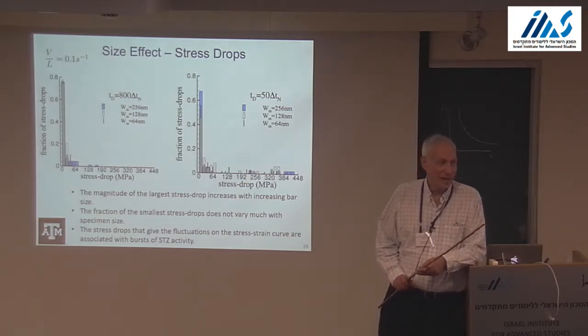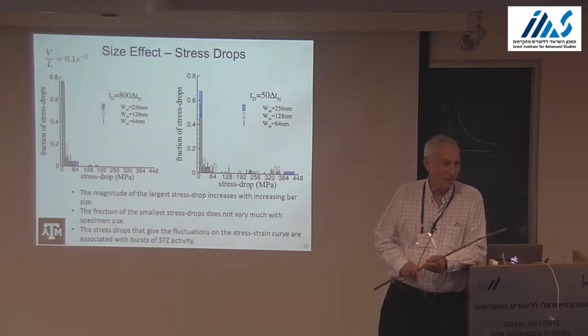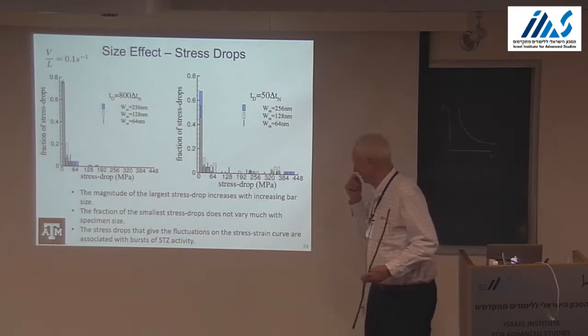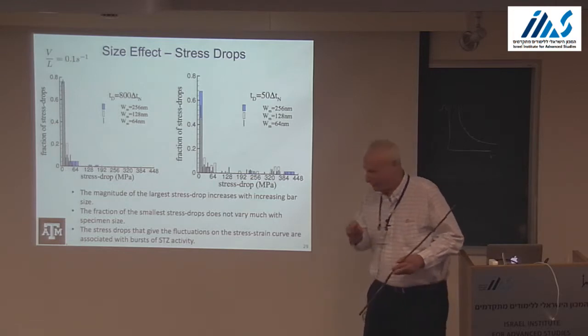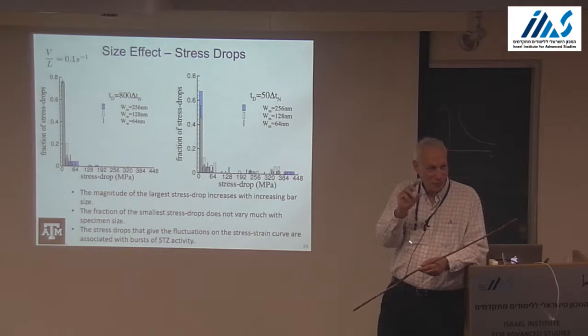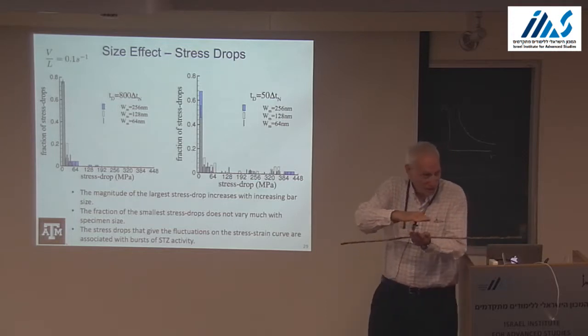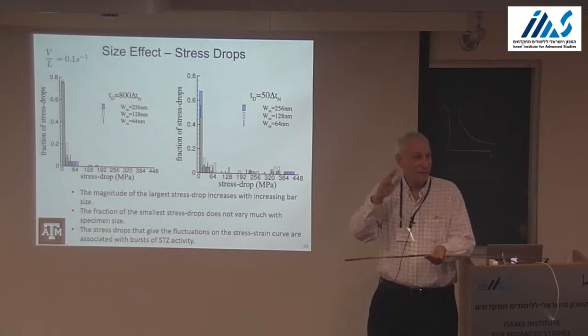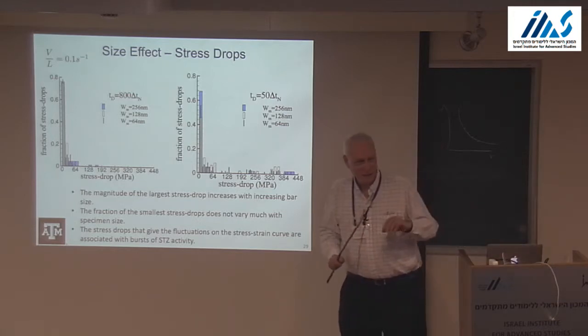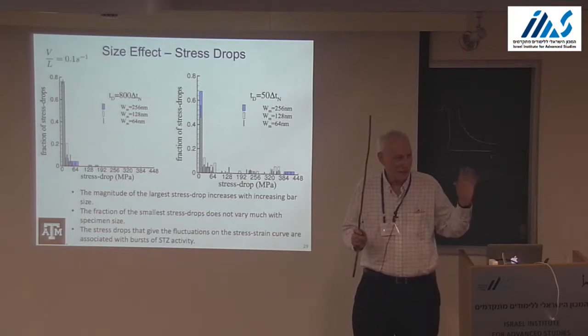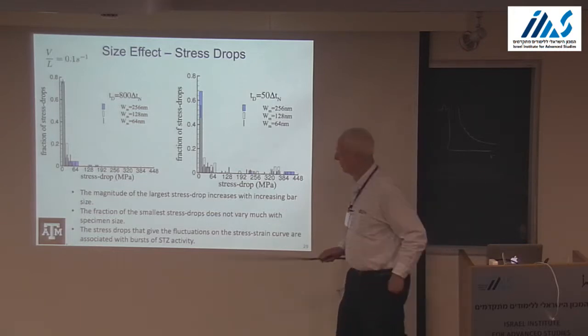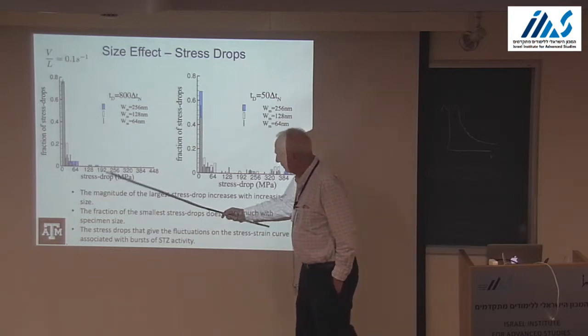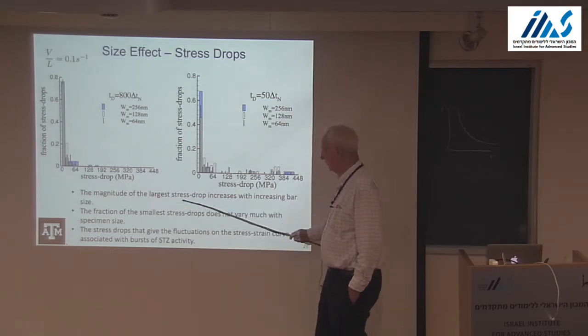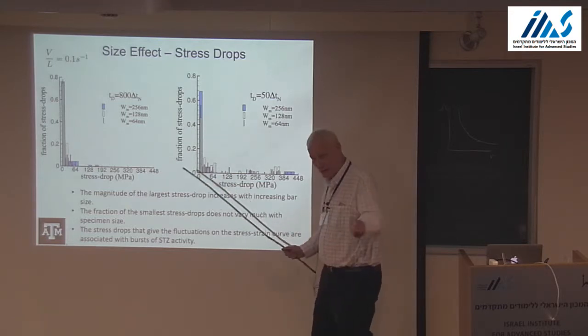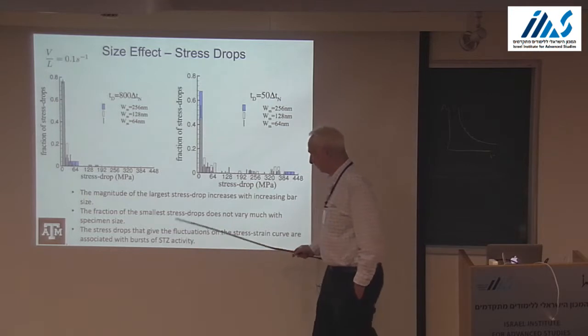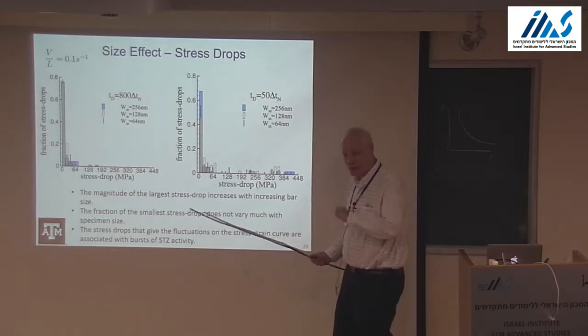The width? Yes, we do. It's in a paper we wrote, but if I remember correctly, depending on the size, we get some widths that initially increase a bit and then seem to stabilize. That's what comes out. I think it's maybe on the order of 10 to 60 nanometer widths, but I don't know the numbers. And you can see the size effect on the stress drop. The magnitude of the largest stress drop increases with the size. The fraction of the smallest stress drop does not vary with size.